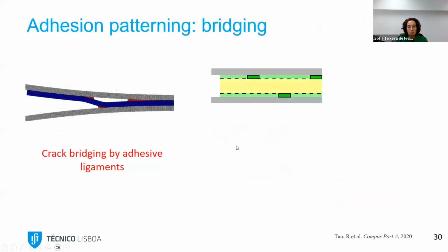In what they did, this is work done by KAUST University in Saudi Arabia by Professor Gilles Lubineau, in which they used exactly this interface failure in order to create different crack fronts. So they used kissing bonds or low interface strength, and they deviated between each other. So they were not on top of each other, but they intercalated. And by doing that, they created adhesive bridging, adhesive ligaments, and created different crack fronts.